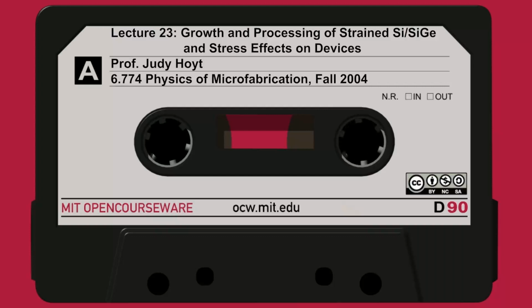What are some of the materials issues if you're growing this relaxed silicon germanium? Well, I already mentioned the threading dislocation density. It actually decreases if you go to higher growth temperatures because the dislocations can move faster. The problem, though, is you also tend to get a buried strain field that creates a crosshatch. In fact, if you look at a plan view optical micrograph of a relaxed silicon germanium layer, it looks like a plaid shirt. This plaid is that buried strain field causing the surface to undulate ever so slightly, maybe 100 angstrom high, hills and valleys, very smooth, and the period or spacing of these undulations is quite large. It can be microns.